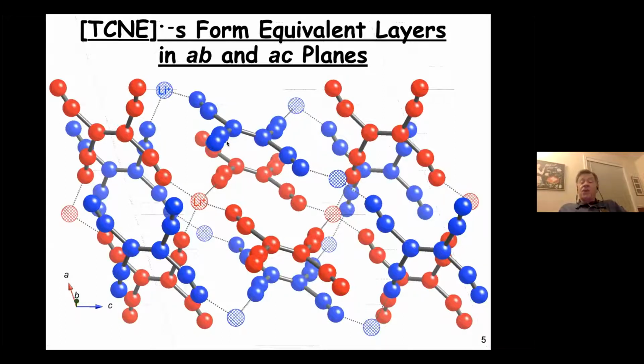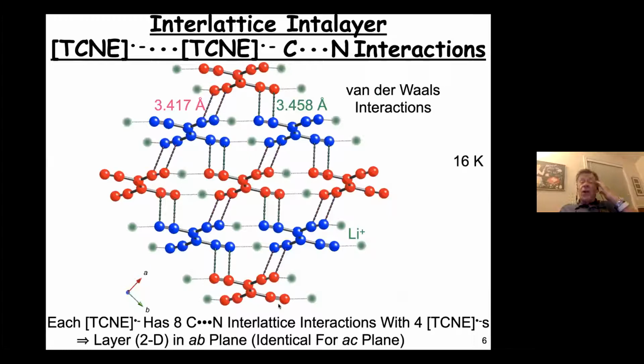So this is the structure of the material, and both of those layers are mathematically and chemically equivalent to each other. So you have a basic feeling for the structure. If we look at any one of those 2 layers, the red and blue are interpenetrating lattices, so they're in different lattices. You can see the CN van der Waals interactions around 3.417 angstroms on one side, and a little bit larger, 3.46 angstroms on the other side. So each TCNE has 8 CN interactions with 4 TCNEs, and they form a layer either in the AB or equivalently in the AC plane.